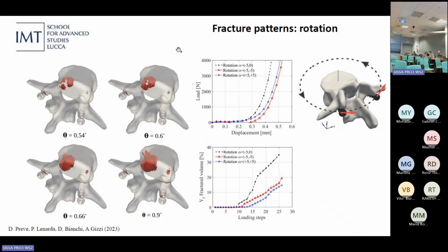This is for what regards the rotation. Applying a displacement here, rotating, we can see that the symmetry is somewhat broken, because we have not a symmetric evolution of the damage inside the cortical part of the bone. We can see that the damaged part involves only the head of the screw, which is basically the direction of rotation.